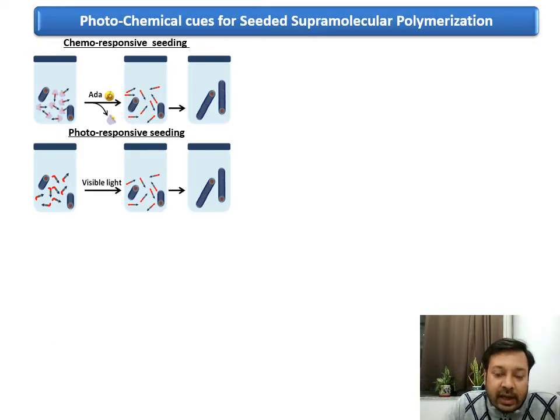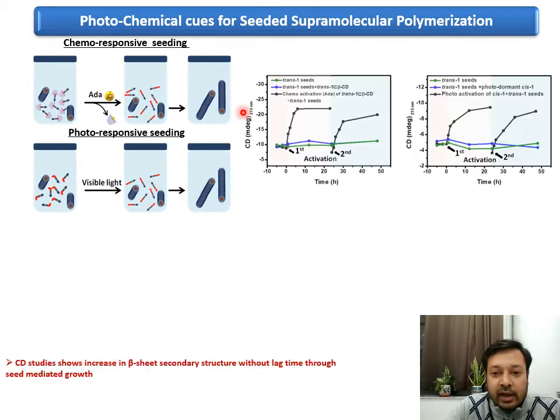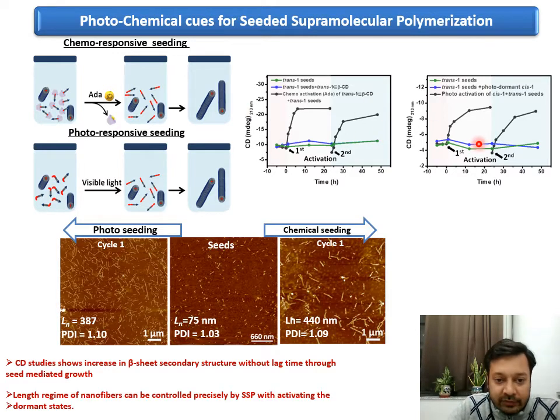Now, we also have controlled the structural precision of the nanomaterial. So we took this preformed seed and put some of this chemo dormant state or photo dormant state, and using a chemo activation or photo activation, you can release such activated monomer, which goes on, and we follow it by CD, and you can follow the growth by CD. And we have seen, upon the seeded growth, you can control very nicely the PDI of such material.